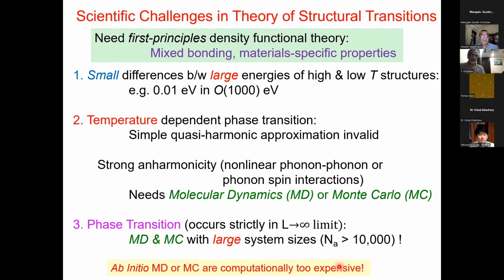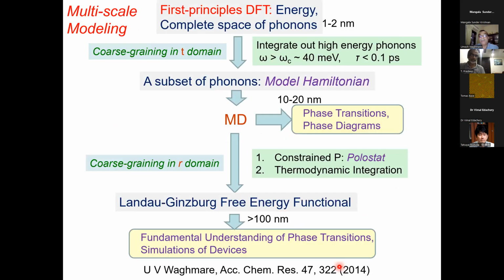Okay, so in the background of these challenges, the approach that my group takes is called the multi-scale modeling strategy, where we start with first principles calculations, where we have access to the full space of phonons, but only length scales of 1 to 2 nanometers. And then we use the technique of coarse graining in the time domain and integrate out all the high energy phonons from the system, and arrive at a subset of phonons for which we develop a model Hamiltonian, which can be simulated in molecular dynamics and allows us to access 10 to 20 nanometers of length scale. And with this, we can predict phase transitions and phase diagrams.